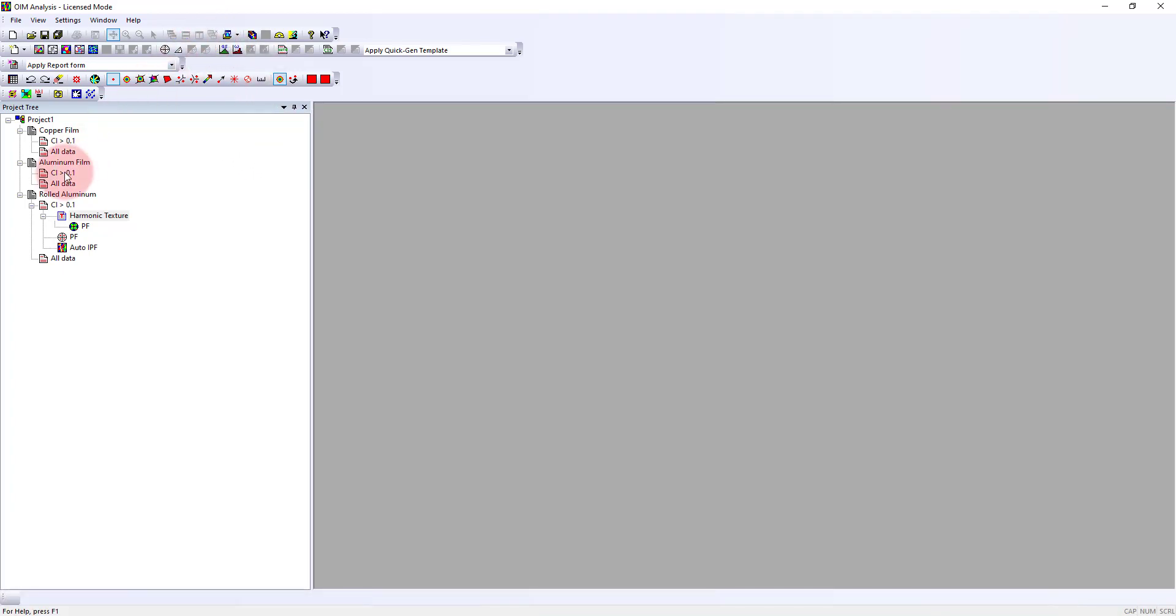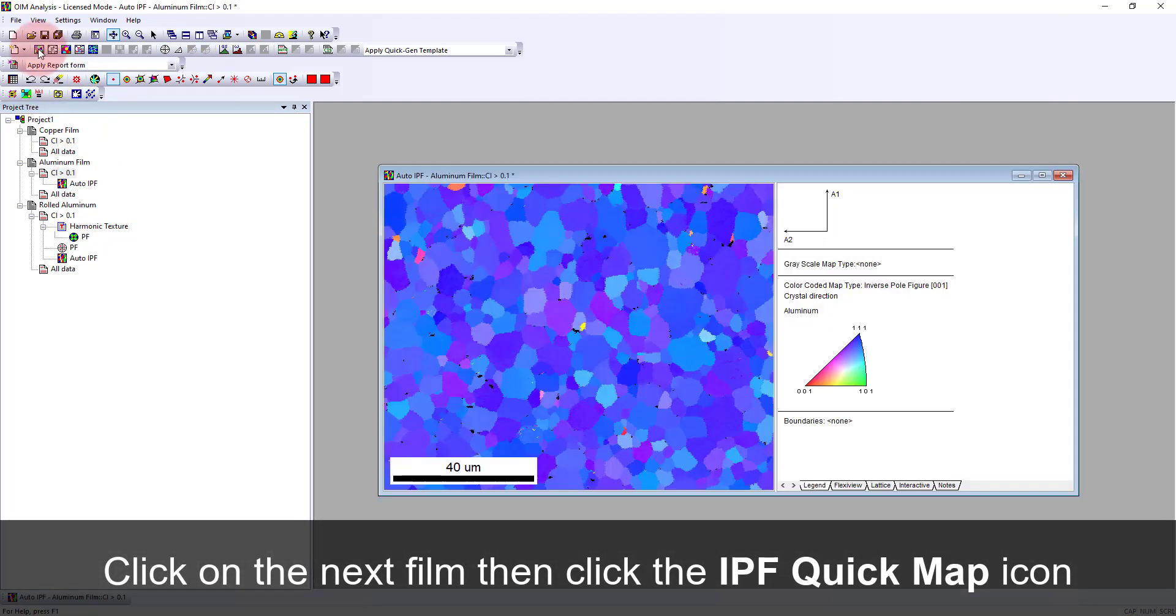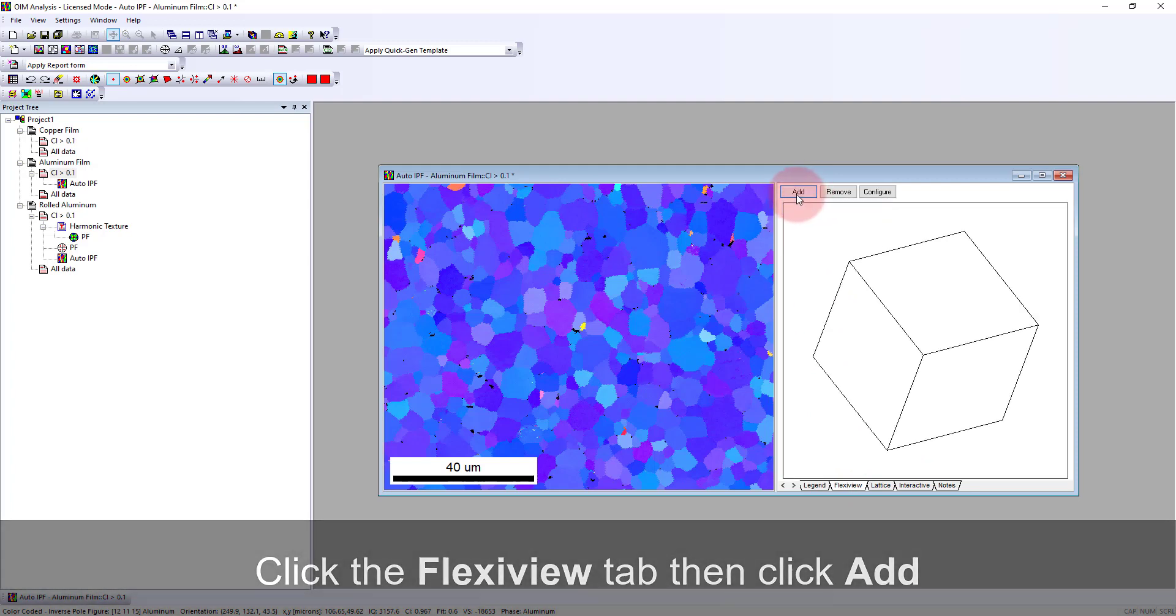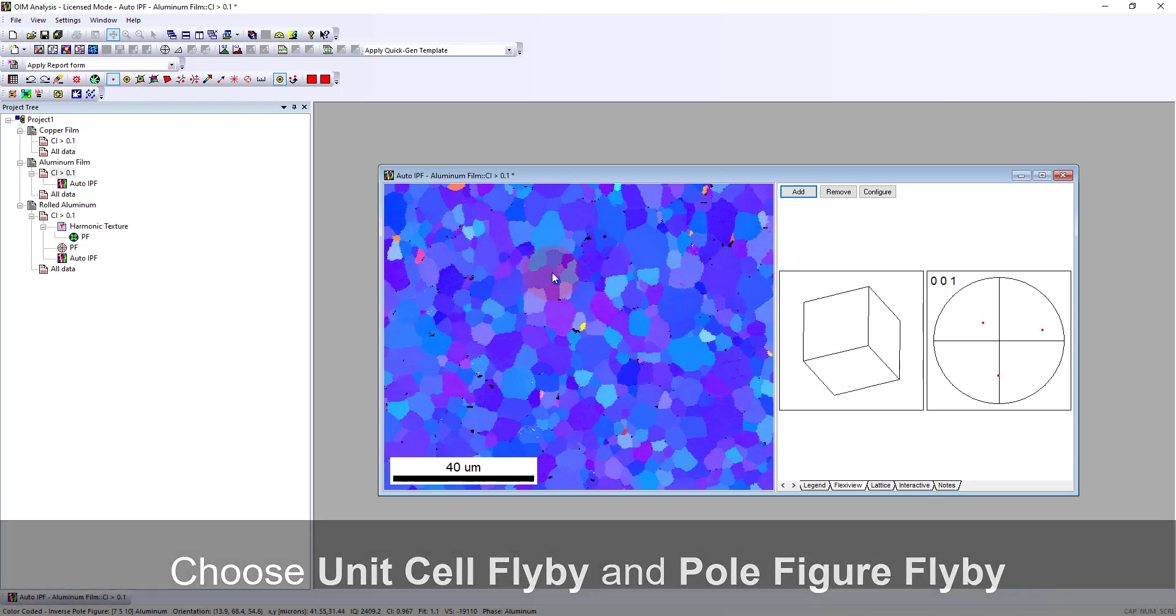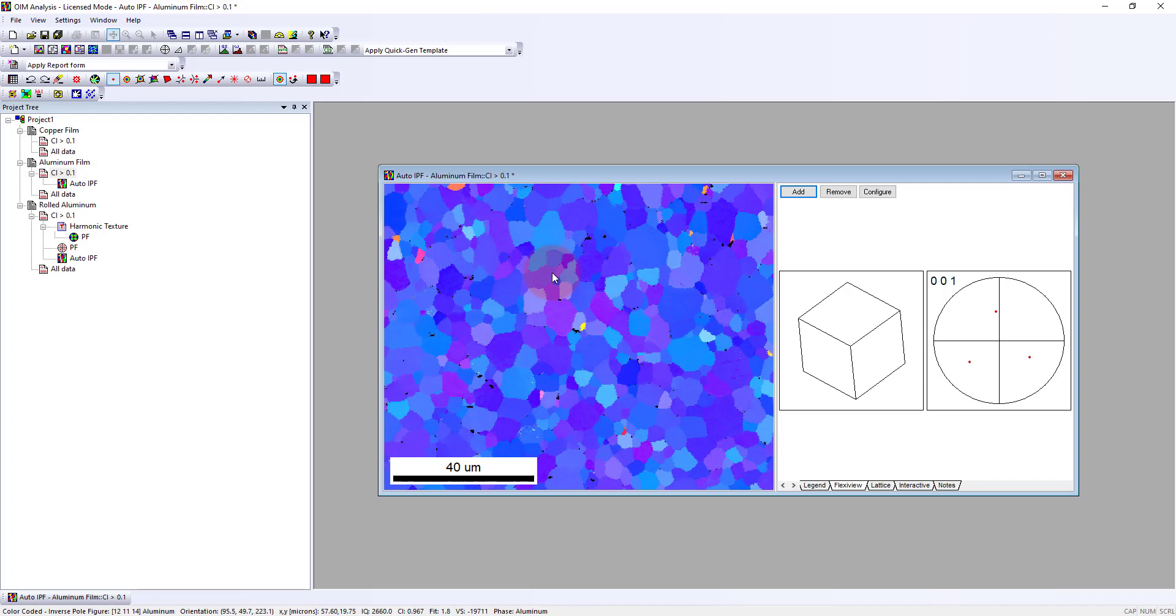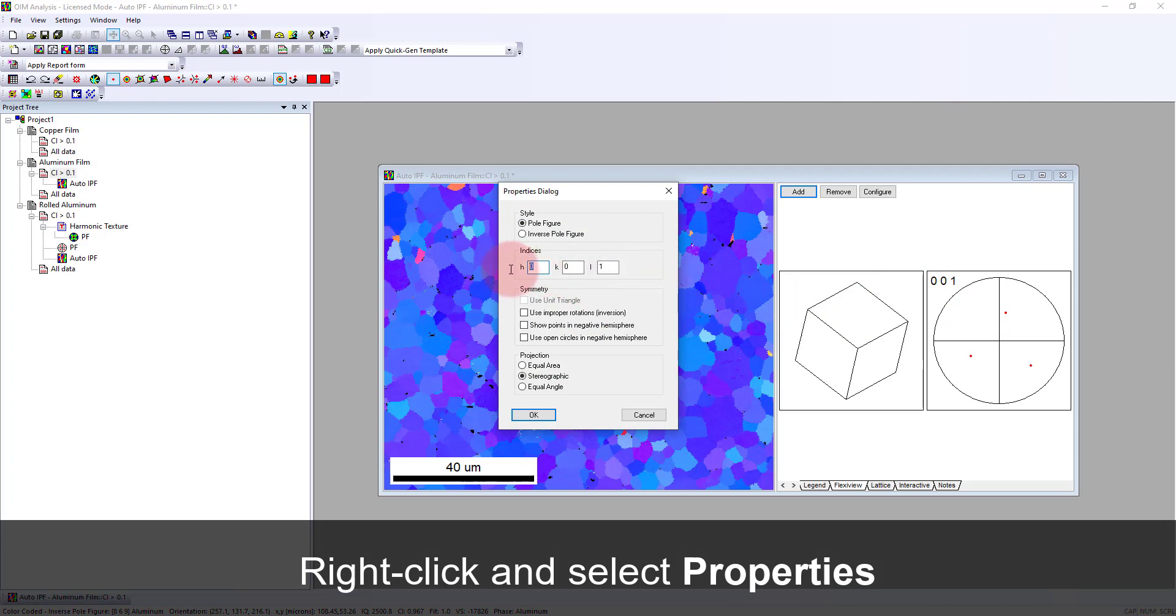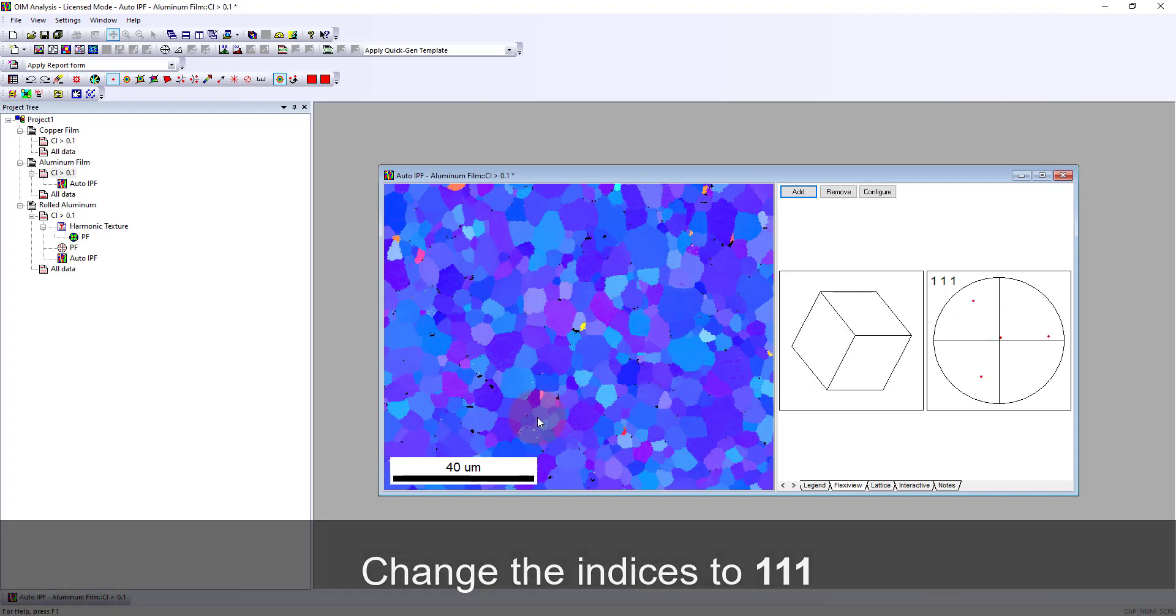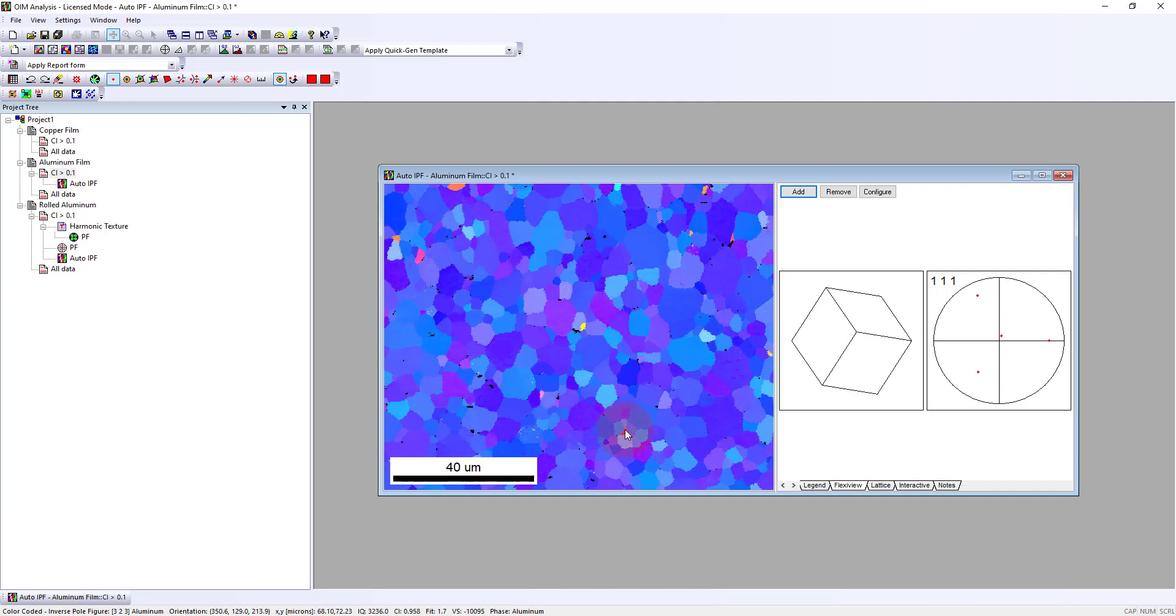Now I'm going to go to the next film, which instead of being a rolled material is going to have a single color facing out. If we look at our flexi view with the unit cell and pole figure, the crystals are all pointing with a blue color, which means it's 111. The point of the crystal is generally always pointing out of the surface. I can right-click here and say instead of 001, let's look at the 111 orientation. Now we'll see that center one is always near the center of the measurement.